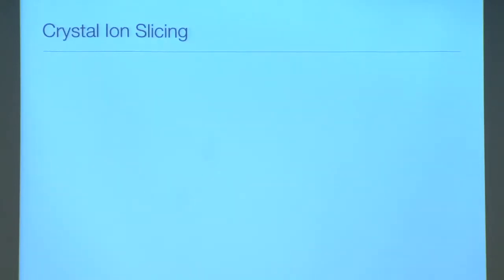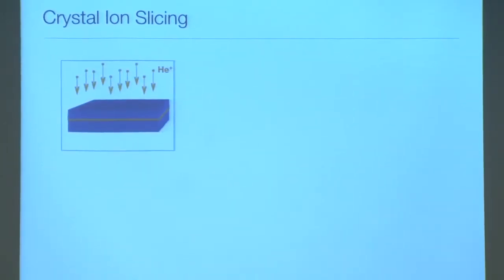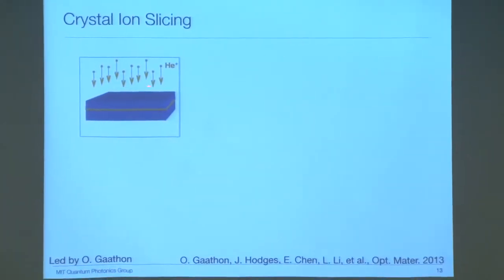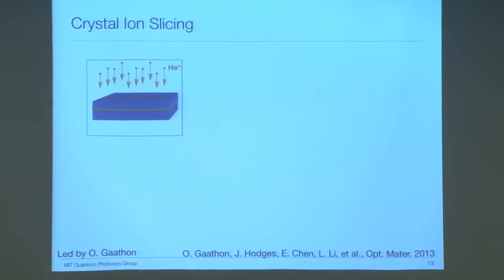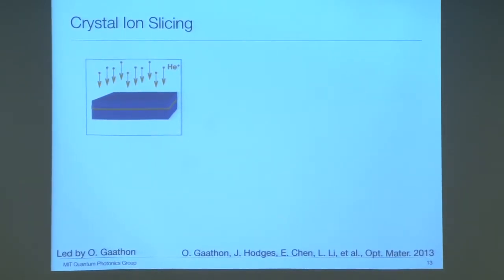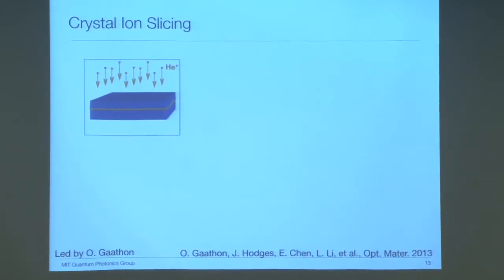fabrication. And we first tried crystal ion slicing, which was a similar technique as the smart cut technique for silicon on insulator wafers. And this project was led by Ophir, our former postdoc. And first we implanted helium ions to create a heavily damaged layer 2.5 micron below the diamond surface.